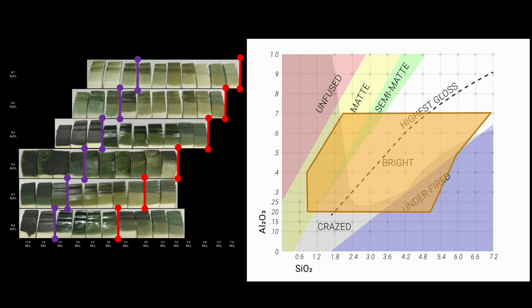We have the purple border that represents the 5:1 silica to alumina ratio, and you can perfectly see how tiles start to get matte until they dry up, given the high levels of alumina. And then on the right-hand side, you have the red area that delimits our 12:1 silica to alumina ratio, where glazes dry up again, given the excess of silica in the system.